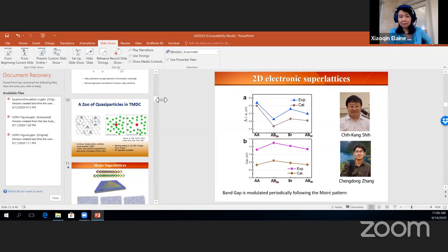Right. So how the dielectric layer changes the binding is more subtle than I made it sound. Our collaborators have systematically studied how these transitions change with the dielectric constant of the environment. They changed to different substrates. And it's not as simple as the binding energy just changing and you see a huge shift in the resonance position. I think partially because the band gap and the binding energy all change in the same direction, which made the absolute energy change different. So this is what people like Tony Heinz call Coulomb engineering. What he meant is because you can play with a substrate, you are changing the Coulomb field environment. But it's a little more subtle than changing it to three dimensions.